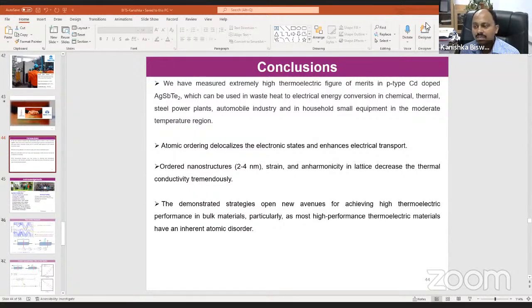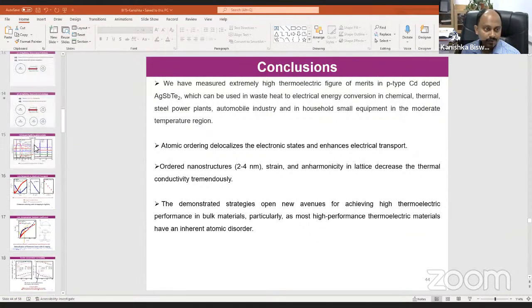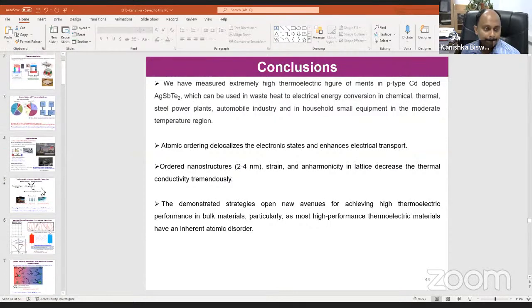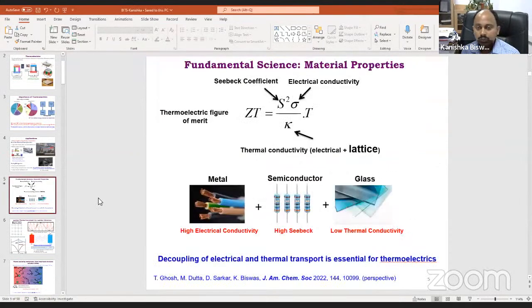So actually metal oxides are not very good for thermoelectrics, because I'll go to this diagram, what I said slowly. See, metal oxides are generally insulators with band gaps in the range of say 3 to 4 electron volt. So once you have a very high band gap, you cannot get metal-like conductivity so easily. And then in oxide, you are working with a lighter element, right? Your thermal conductivity will fall in the range of 40 to 50 or 30 to 40 watt per meter Kelvin. Whereas I am starting in telluride from 2-3 watt per meter Kelvin, and we are bringing it down to around 0.2 to 0.3 watt per meter Kelvin.